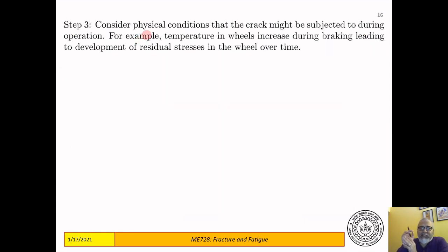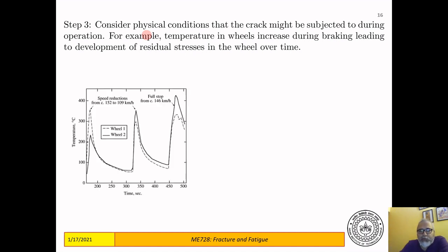The next step is to consider physical conditions that the crack might be subjected to during operation. So let us shift from an axle crack to a crack in the wheel. The wheel is subjected to huge temperature rises whenever the train brakes. This is a high-speed train, remember. So whenever it brakes, the temperature at the contact between the wheel and the rail increases tremendously. These go up to 400, 500 degrees centigrade, and this actually has to be taken into account. This is an operating condition that happens for a short duration during braking, but it has to be taken into account in designing the wheel.